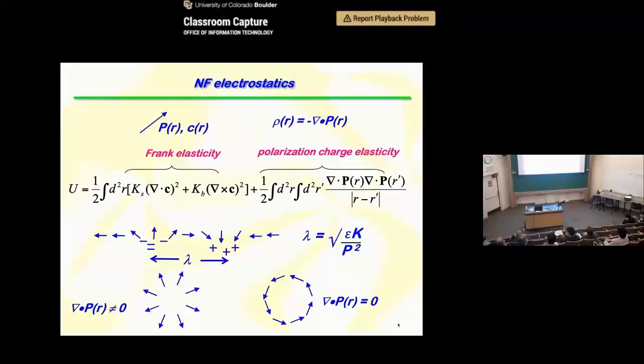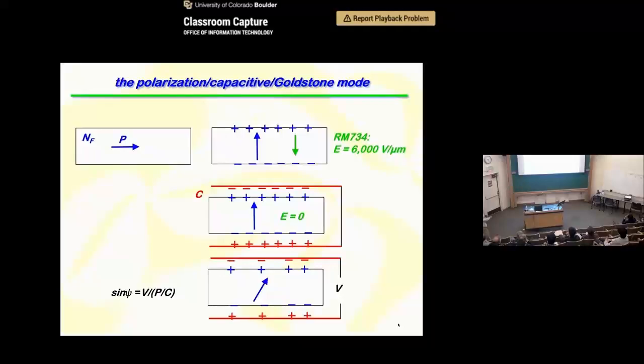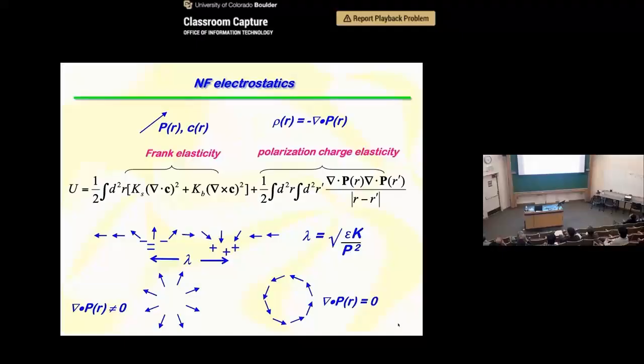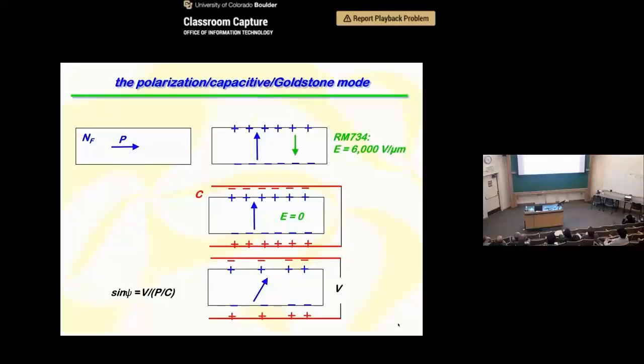Okay, so one way to escape polarization charge is going around in circles. So if you have bend defects, you have div P equal to 0. On the other hand, splay defects will have space charge. Okay, then this is the bulk space charge term, but then there's also a surface polarization, P dot the normal to a surface, where the polarization ends.